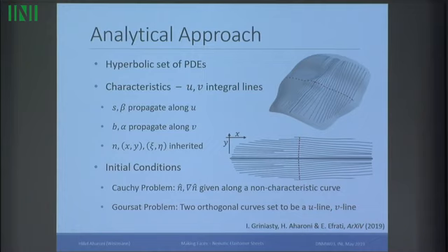So basically, the initial condition is given along characteristics. Half the information is given along one characteristic curve, another half is given along a second characteristic curve. I guess the easiest setup for this is to take two curves on my target geometry, any two curves on the face that are orthogonal at the point where they meet, and decide that I want the blue curve to be parallel to the director everywhere, and that the red curve should be perpendicular to the director everywhere.